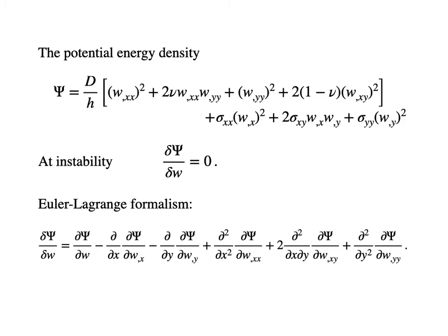To have something more than this, that is the part required for formulating a finite element theory, we also would like to have the partial differential equation, which you get easily from the expression in the middle, the variation. And it's the Euler-Lagrange formalism that gives you the derivatives, and you treat then the displacement and the displacement's derivatives, the slope and the curvature, as individual independent variables.